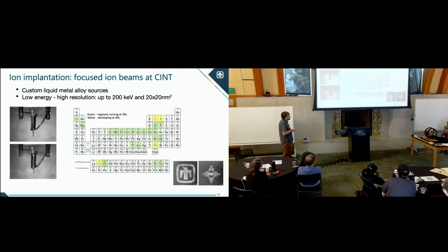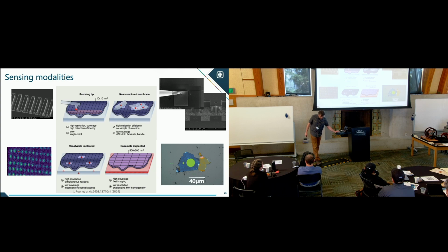And actually down here, the length scale is 5 microns. We implanted with our focused ion beam at Sandia and patterned silicon vacancies and did photoluminescence to get these images, almost like an invisible ink that you have to have the right laser to see. All right, so I've talked about how you can get nitrogen vacancies into diamond. Now we're actually going to move into actual quantum sensing. So I mentioned earlier that the most important thing is getting your nitrogen vacancy close to something. All right, and these are kind of the major ways that one does this.